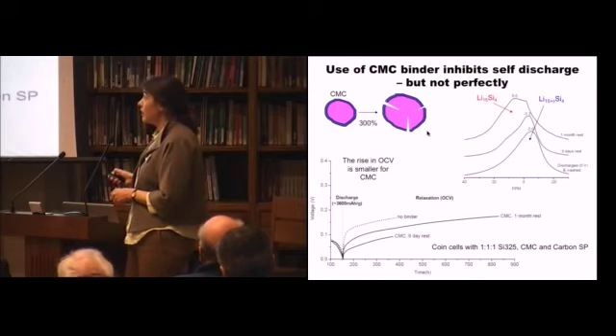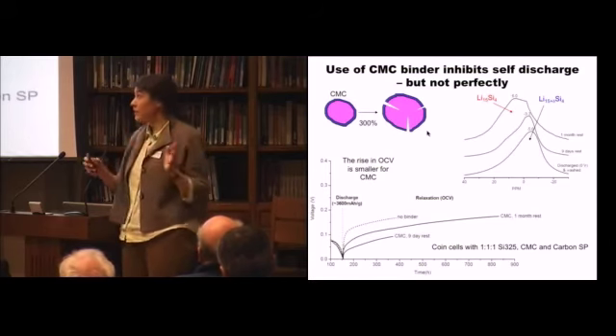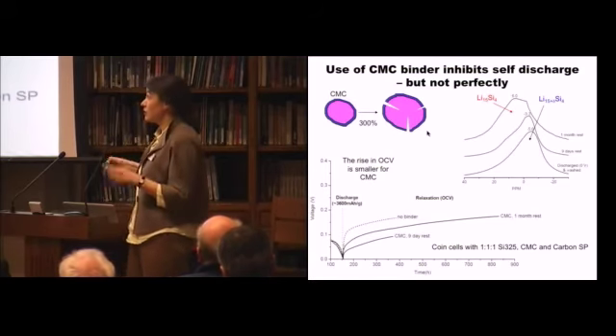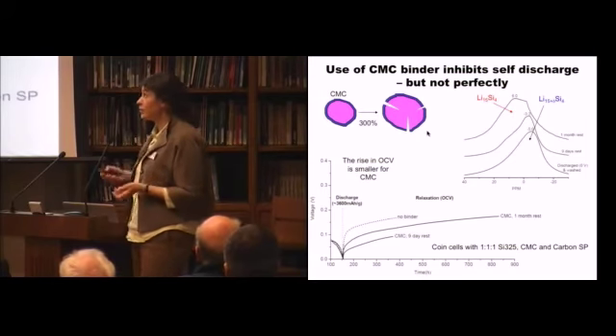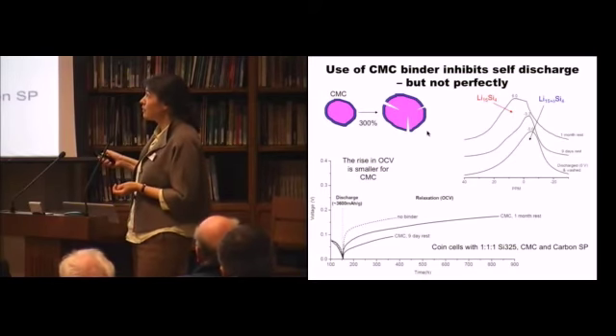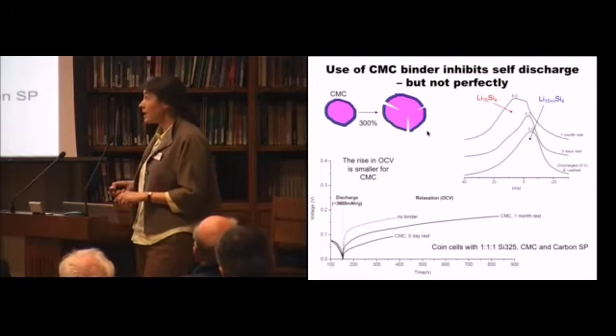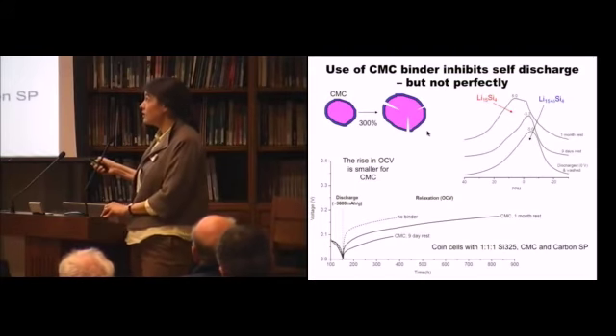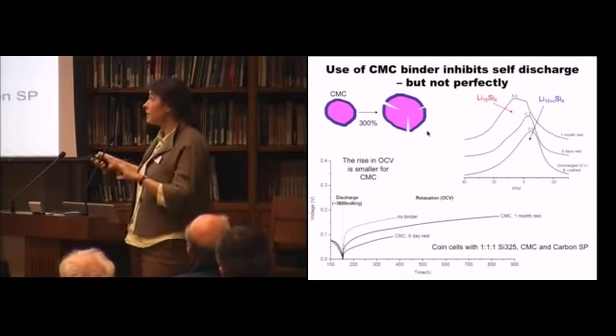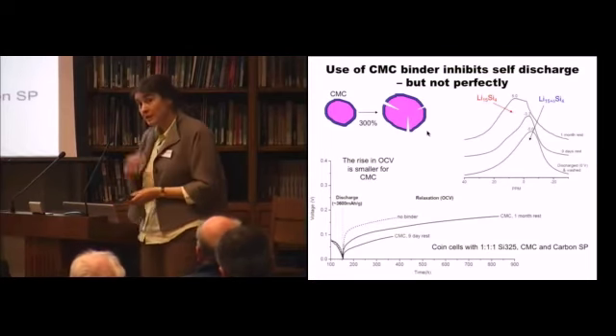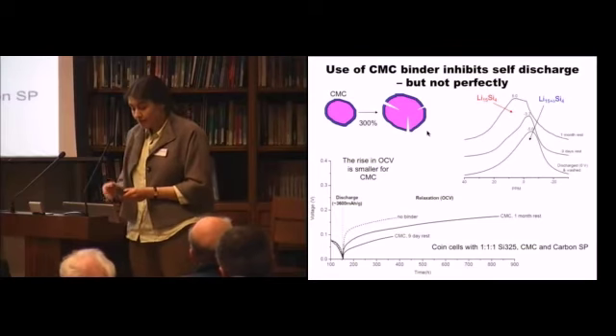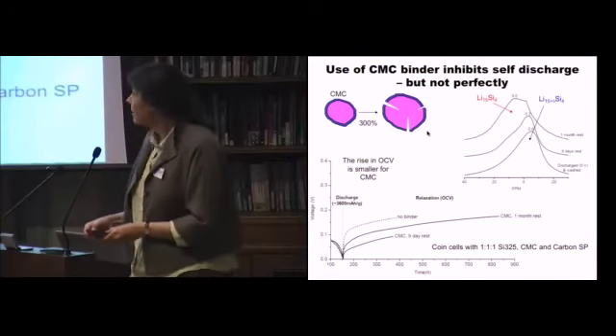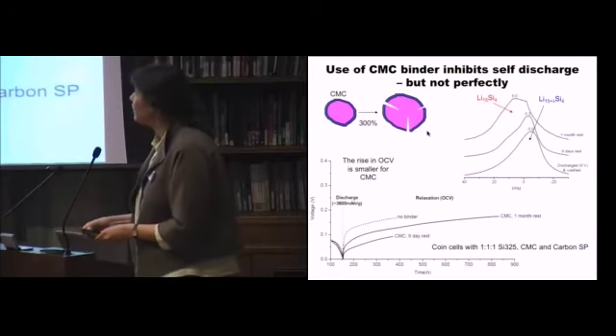Unfortunately, it's not perfect, because as you add lithium into the structures they expand by a tremendous amount, the particles crack, and you expose fresh surface for these reactions. And so the challenge now is for us to try and identify ways of healing the cracks and passivating that surface so that we can slow down these processes so that they take even longer time periods than months.